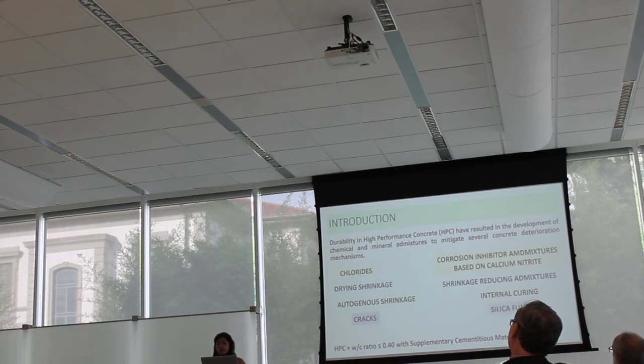You can also use silica fume to densify your concrete, but silica fume is going to increase the autogenous shrinkage. So you have to take this into account when you use silica fume, because it's a difficult material to use, but it's a good one if you know how to use it.